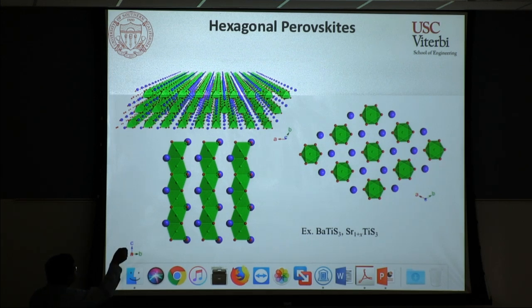These are essentially 1D chain compounds, with octahedra that are connected by the faces, and they form these rigid 1D chains. And if you take the AB face of this compound and look at it, you will clearly see this hexagonal pattern that is very similar to gallium nitride or graphene or other honeycomb systems. When we wanted to study how the light matter interaction happens in this system, is there any anisotropic effect that we could leverage?